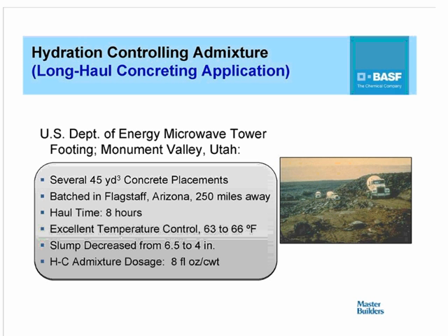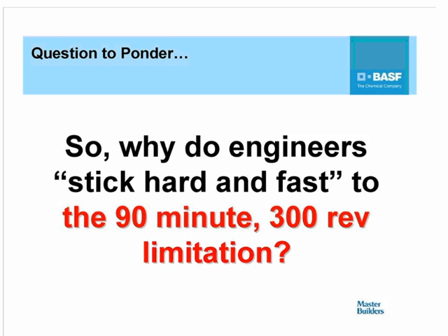And as I indicated, they also facilitate long hauls, such as this particular example that I'm showing, where concrete was hauled a total distance of 250 miles over a time of 8 hours. Upon arrival at the job site, the concrete still had a very decent slump of 4 inches and could be placed without too much problem and without having to add additional water to the mix. In this particular case, a hydration controlling admixture was used at a dosage of 8 fluid ounces per hundredweight of cement. So my question to you is, why is it that engineers stick hard and fast to the 90-minute, 300 revolution limitation when obviously within the industry there are technologies that can be used to permit placement of concrete way beyond these particular limits?